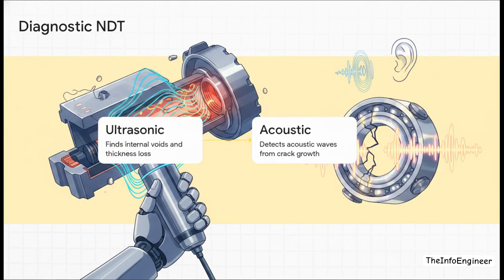But how do we check on machines that are currently out in the field without completely tearing them apart? We use high-tech non-destructive testing, or NDT. The diagnostic steps here are just amazing. We can start with ultrasonic A scans, literally shooting high-frequency sound waves into the metal to see internal voids or thickness loss that is completely invisible to the naked eye. Then, we can use acoustic emission sensors to detect the microscopic acoustic waves generated by internal crack growth. We can literally listen to a bearing scream in distress long before it physically seizes up.